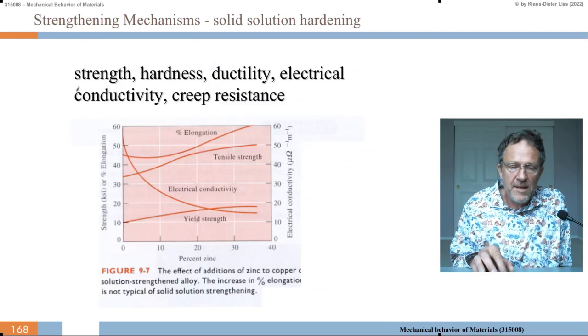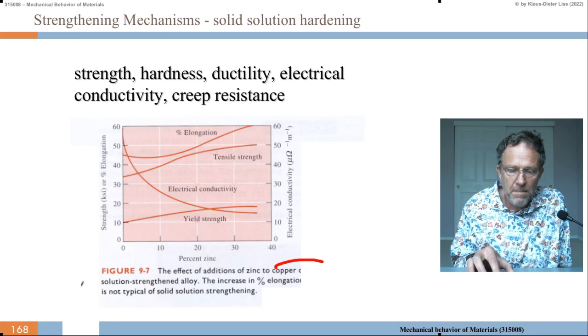Another figure here about the strength, the hardness, ductility, electrical conductivity, and the creep resistance. So this is percent zinc in copper. Here we have it, it's copper. Solid solution strengthened alloy. The increase in percent elongation is not typical of solid solution strengthening. So here we see the yield strength, we see the electric conductivity goes down.